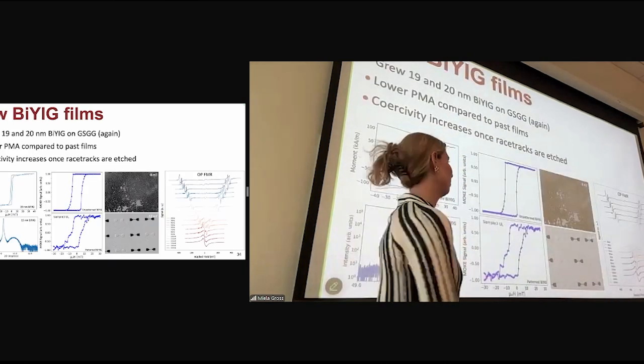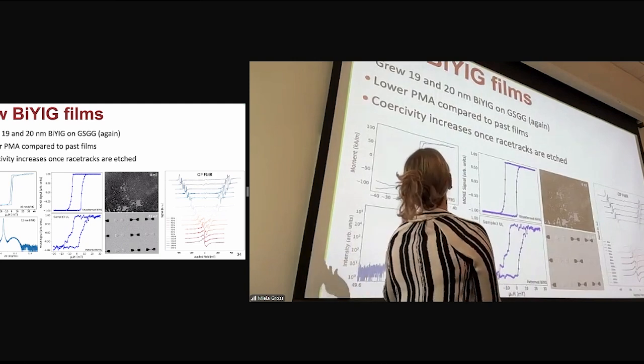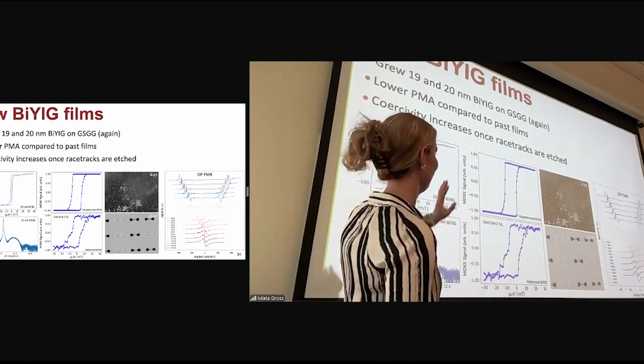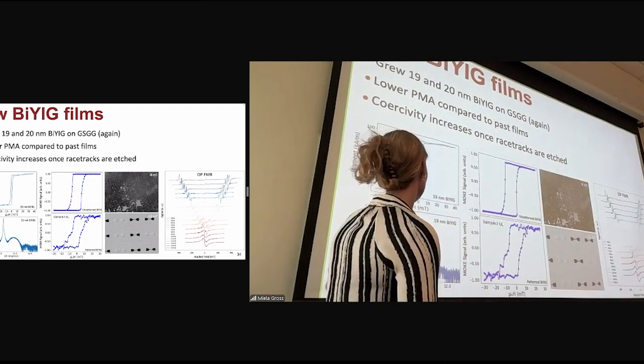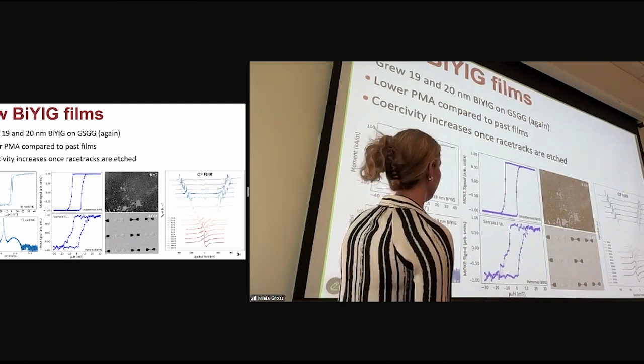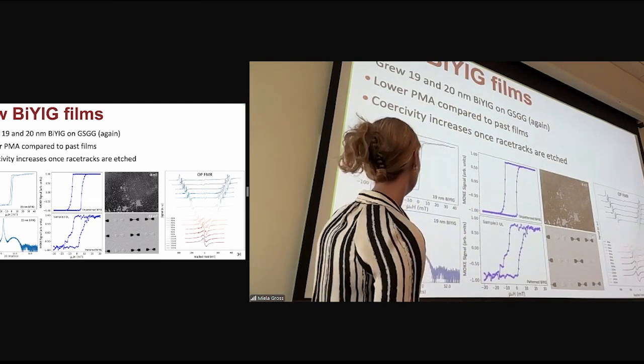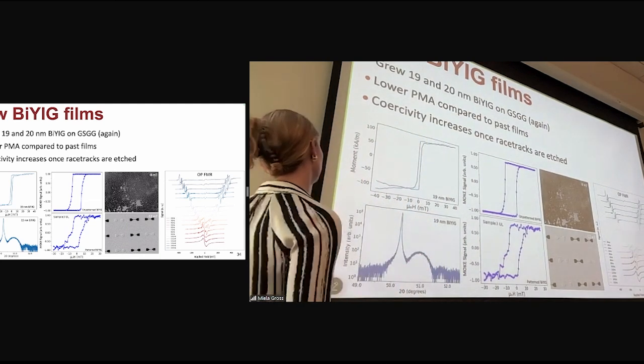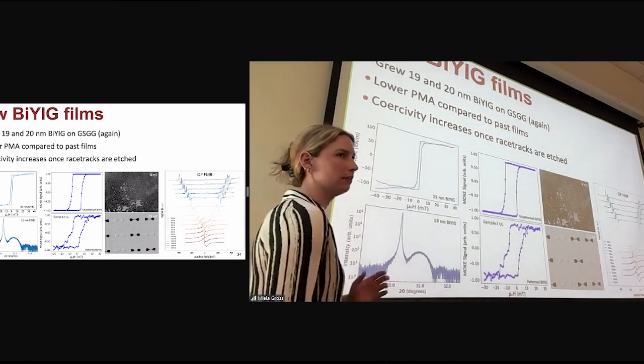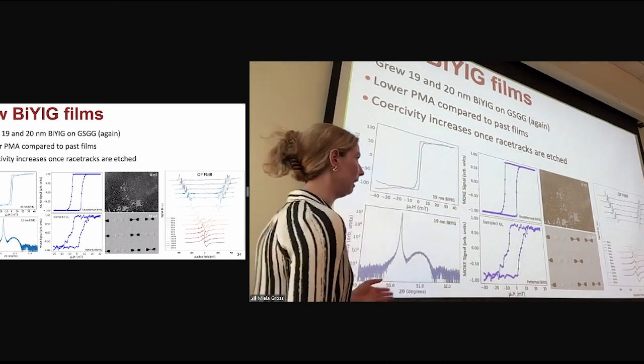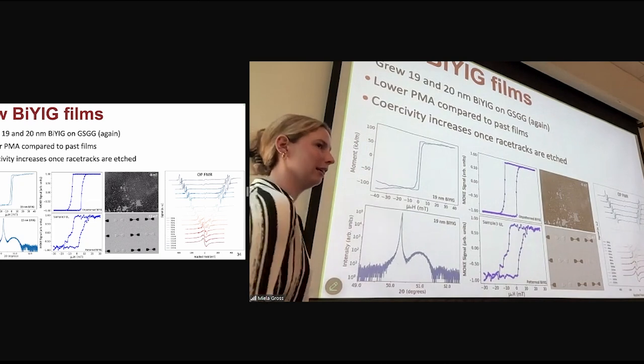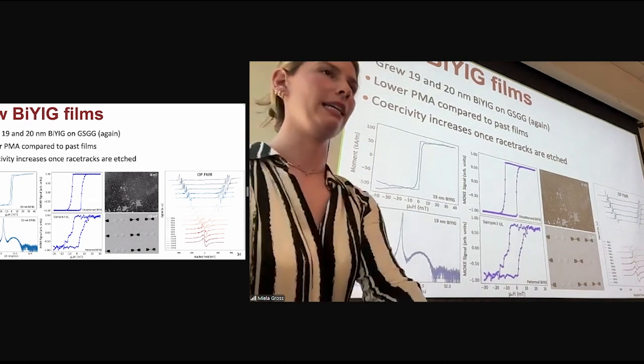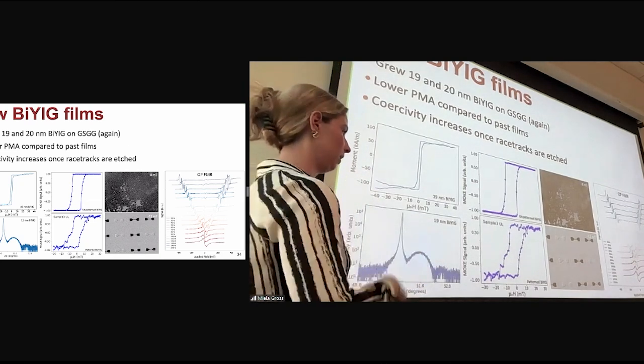So I grew bismuth-YIG again. 19 and 20 nanometers of bismuth-YIG was grown on garnet substrates. We see very similar behavior, like characterization, compared to the past films. The only difference here is we see a little bit lower PMA. That doesn't change anything other than those resonance frequencies that we're using to excite the spin waves.